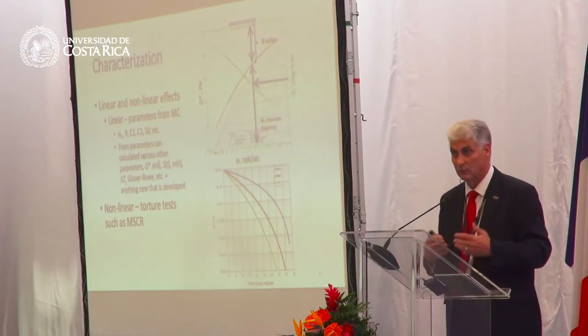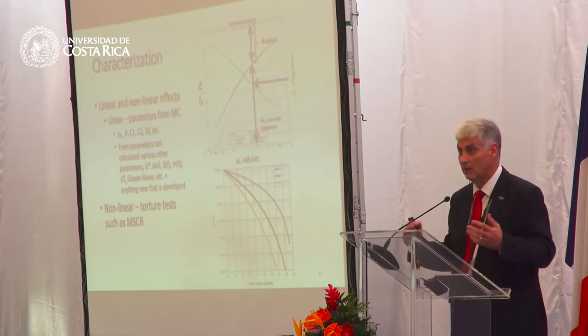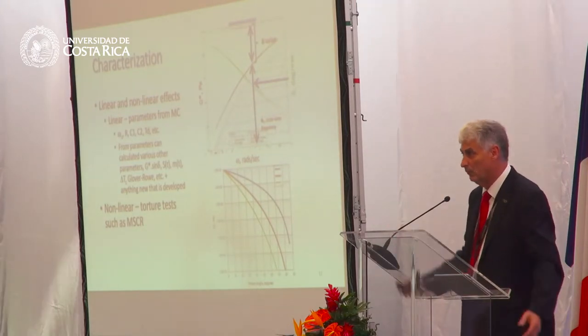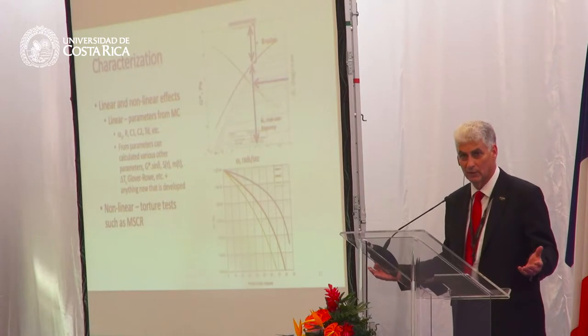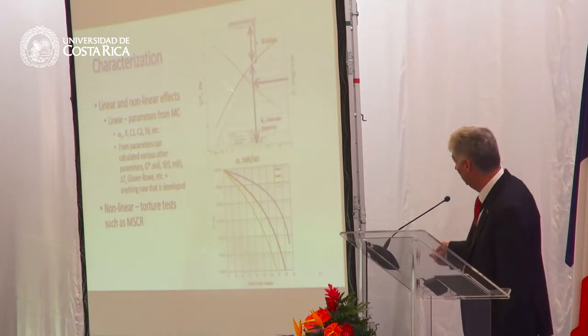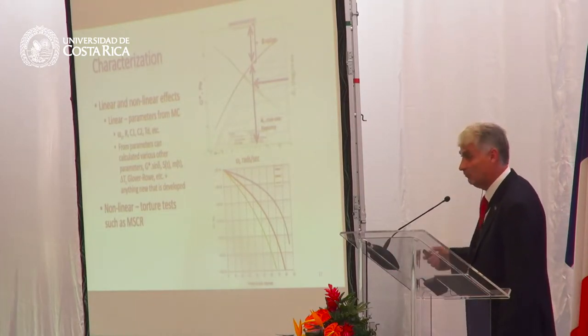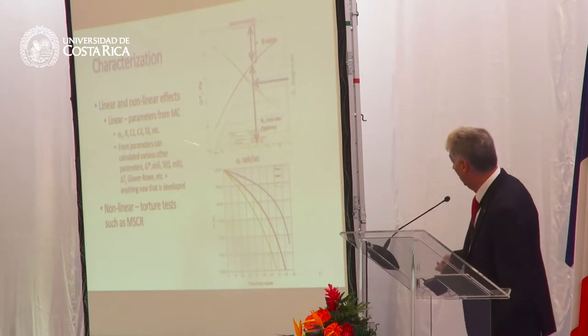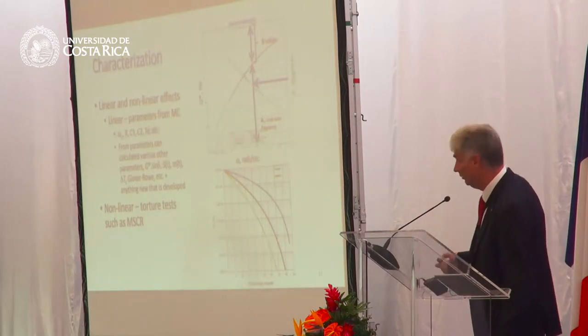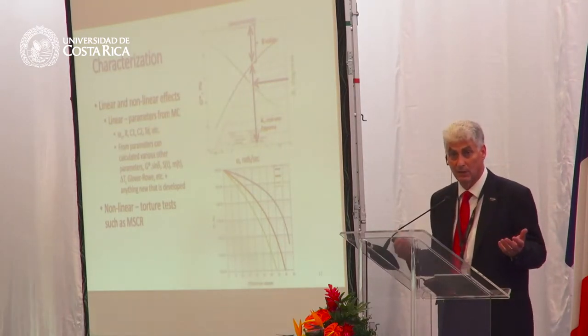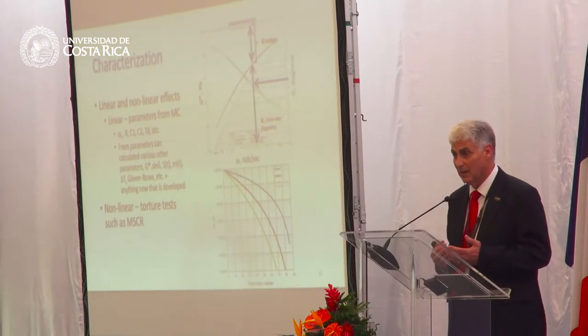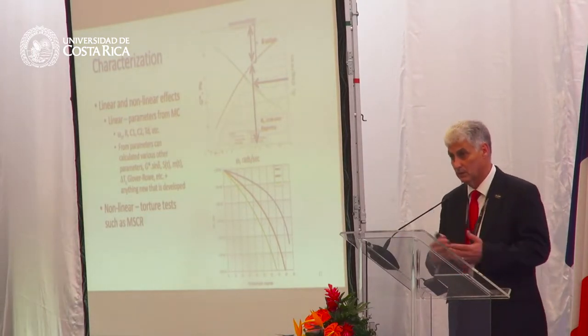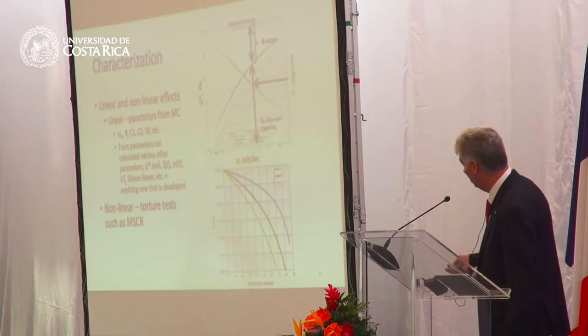It relates to the amount of asphaltenes. It relates to whether you've got a sol or a gel binder. It relates to the critical cracking temperature of the binder. This relates to so much as a characteristic of the binder. Where this point lies, the crossover frequency, tells us whether the asphalt binder has a certain hardness, and so it relates to the hardness of the material.